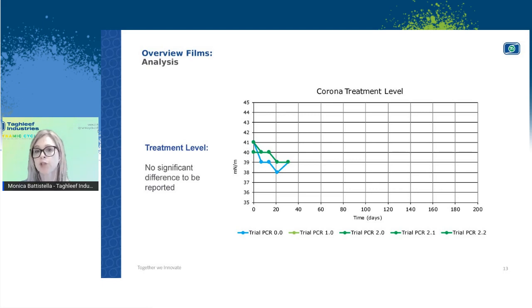And so for us, it was very important to check not only the performance of the film right after the extrusion, but we even followed this parameter over months. And I can also confirm that the first extrusion took place in August 2019, just before COVID started. For this reason, the physical trials when it comes to printing, converting, and lamination took place later, actually more than one year later. They took place towards the end of 2020, and some of them took place last year. And still, it was possible to reuse the film, so to print and laminate it and to make pouches out of it.